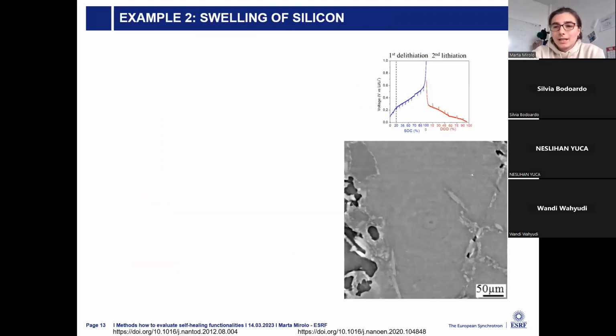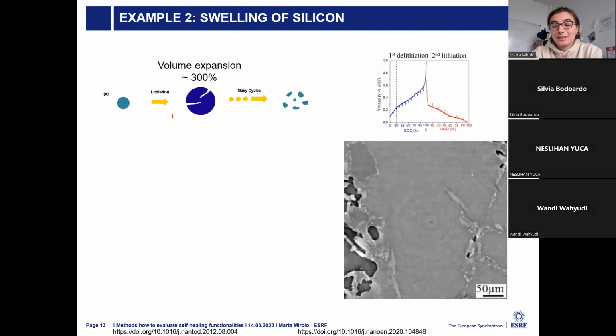So the first example that I will present with imaging is the swelling of silicon. So we already heard that silicon is a promising material for anode, as it has improved specific capacity, with the small drawback of a very large volume expansion up to 300%, which leads to the formation of cracks and crumbling. This case is exactly what was presented before. So by using different binders, we can study how the binders can accommodate the swelling of this particle.